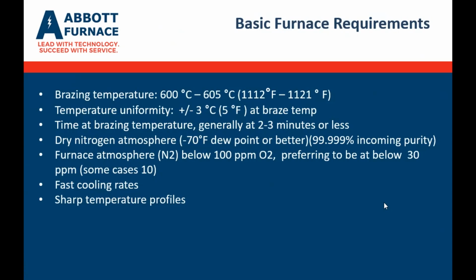As far as the furnace requirements itself, we're looking at 600 to 605 C as a typical brazing temperature of the part. The uniformity across the entire part, including the tubes and headers and fins, must all be plus or minus 3 degrees C, generally at 2 to 3 minutes or less. The nitrogen atmosphere that's required, incoming nitrogen, is negative 70 degrees dew point or better with 5 nines, or 99.999, incoming purity.